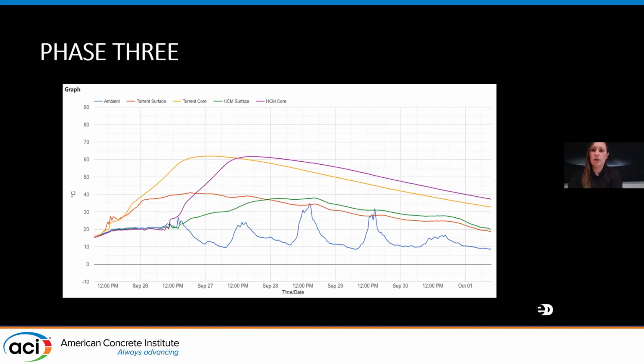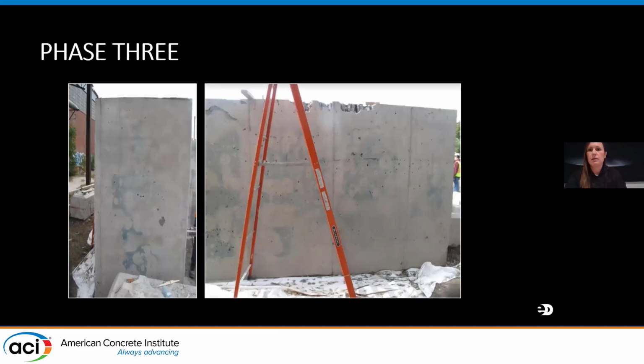Thermal monitoring was performed for both mock-up elements with placing temperatures of 25 degrees Celsius. The maximum heat of hydration can be seen to be just above 60 when shot into a 1.3 meter wall. 2 days after the mock-ups were shot and the shotcrete had attained sufficient strength, the bracing and the forms were removed. This enabled the examination of the quality of the shotcrete consolidation at the stripped form faces. Upon examination of the stripped faces, it was readily apparent that they were able to generally achieve excellent consolidation of the shotcrete right to the back of the wall.